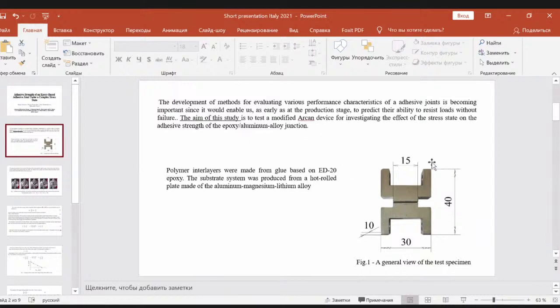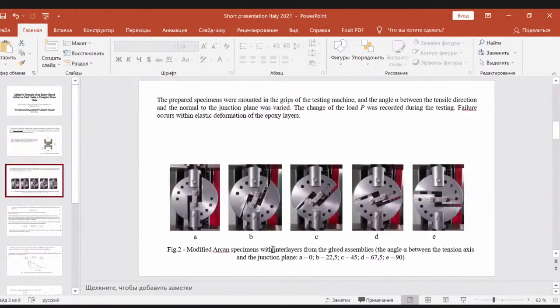Polymer interlayers were made from a glue based on ED20 epoxy. The substrate system was produced from a hot-rolled plate made of aluminum, magnesium, lithium alloy. In figure 1, we see a general view of the test specimen. The prepared specimens were mounted in the grips of the testing machine, and the angle alpha between the tensile direction and the normal of the junction plane was varied. The change of the load P was recorded during the testing. Failure occurs within elastic deformation of the epoxy layers.